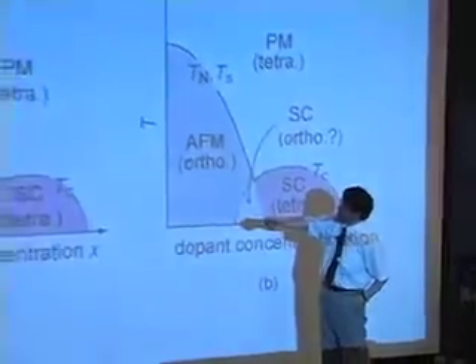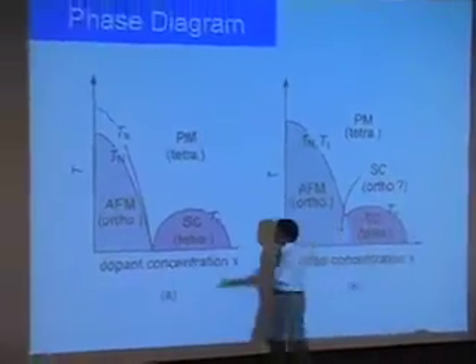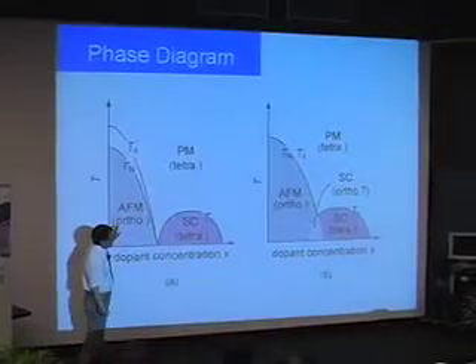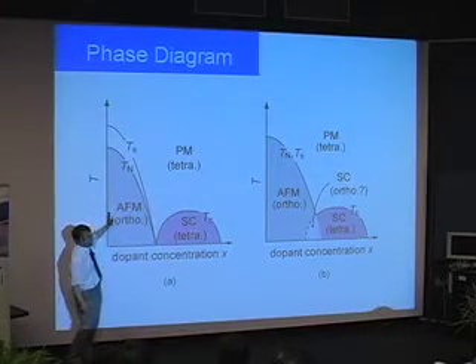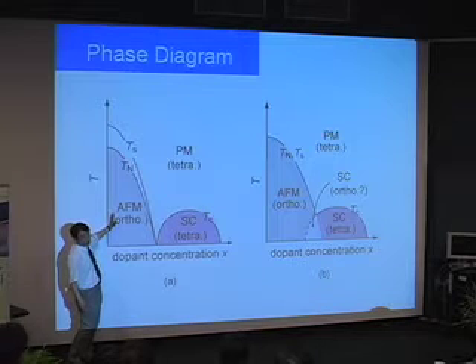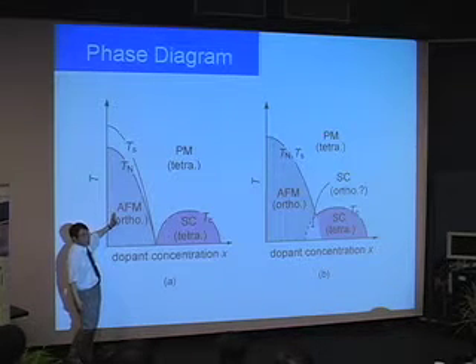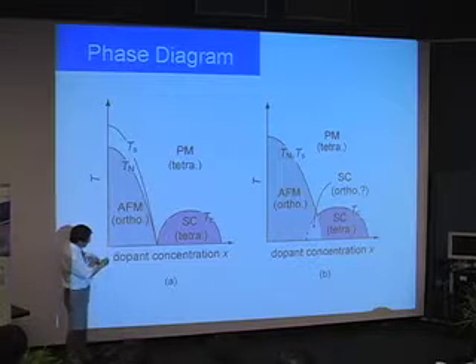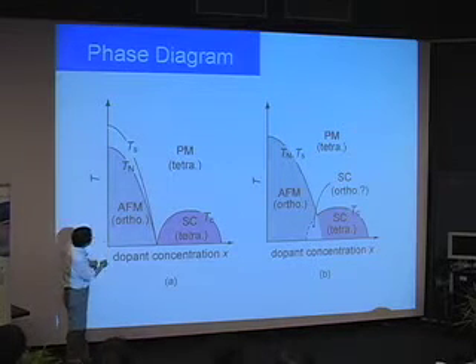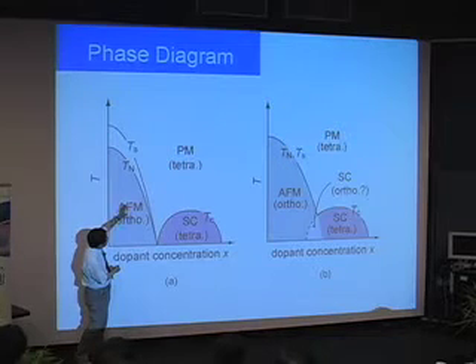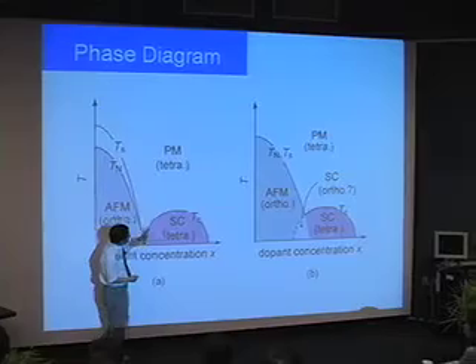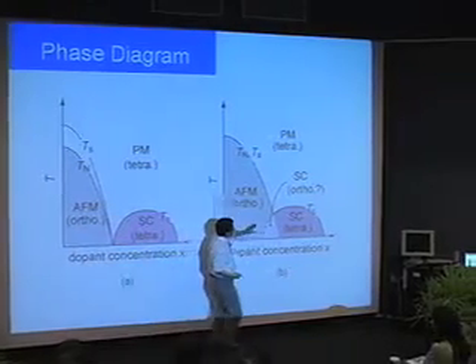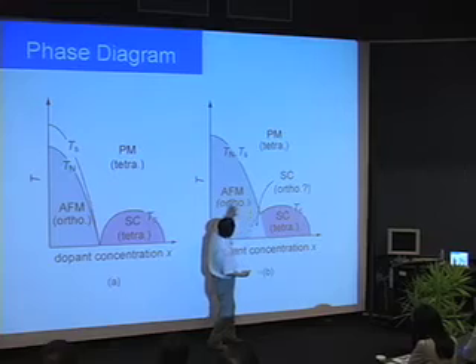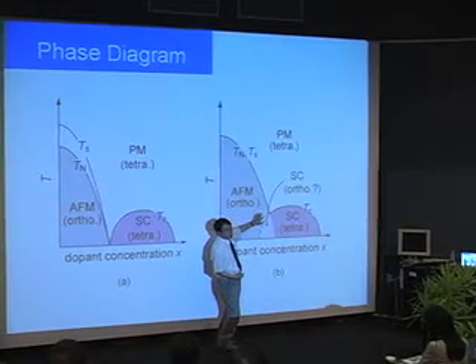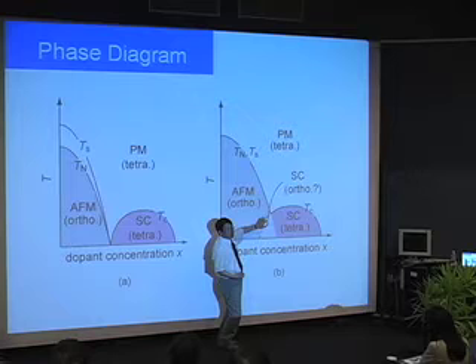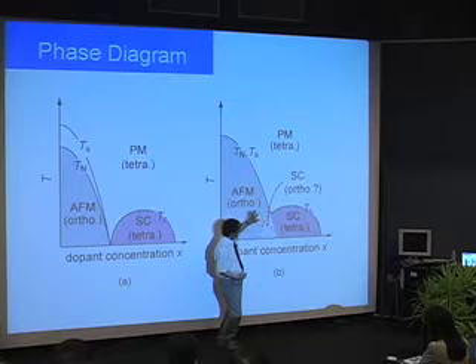For the electron-doped case, the parent material is an antiferromagnetic metal, while for the cuprate it's an antiferromagnetic insulator—totally different materials, but the antiferromagnetic state is the same. When electrons are doped, the antiferromagnetic phase disappears, and at that boundary superconductivity emerges. Sometimes the superconducting and antiferromagnetic states look coexistent, but this is not true coexistence.